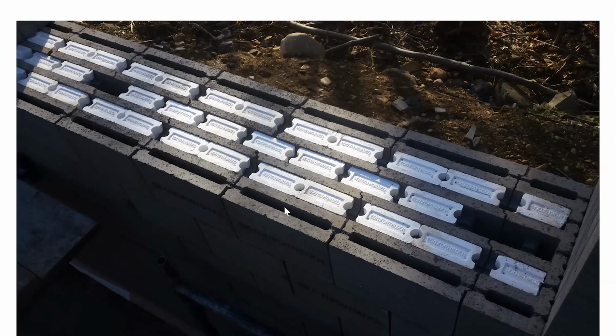Then it's also cured. The concrete is manufactured inside, as you can imagine. So we have incredible control over the amount of moisture that we can put in. We have microwave moisture probes in our aggregate bins so that we can dose the aggregate precisely by volume, so that it is always tied by volume to the cement. It's incredibly difficult to do when you have a ready mix situation. I know, because we had ready mix. So when you manufacture a concrete block or a paver or something in a factory setting, you are able to do all this, and you can run exactly the moisture you need in order to maximize the cement and activate the cement.